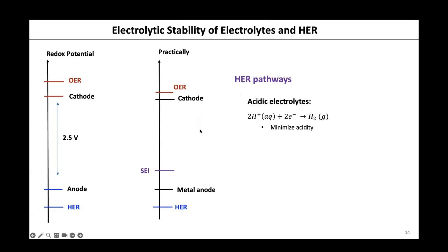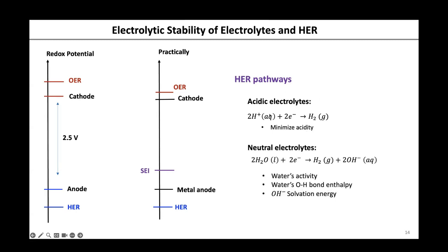Now, talking about hydrogen evolution, what are the pathways for this parasitic reaction to take place? If your electrolyte is an acidic electrolyte, you're going to have a lot of protons. So protons will take the priority to be reduced over water. Protons are a better acid than water, so protons will be reduced first. Now, how to address that? Well, the solution is to make the acid not so acidic, to minimize the acidity. Another pathway is when you have a relatively neutral electrolyte, right? The pH value is maybe 6 to 8 or 5 to 9. It's not so acidic, so the species to be reduced is going to be water. You're going to have water reduced instead of protons.